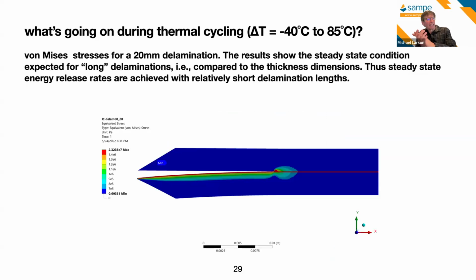And here is where I mentioned the self-similar nature. Once you get a long enough delamination, you get pictures looking like this, where this is the von Mises equivalent stress in a geometry. And once you get away from either the chamfer or away from the edge, because of the ratio of the length in the horizontal direction much bigger than the dimension vertically, you end up with a self-similar sort of growth, that as this delamination proceeds, this field looks the same.